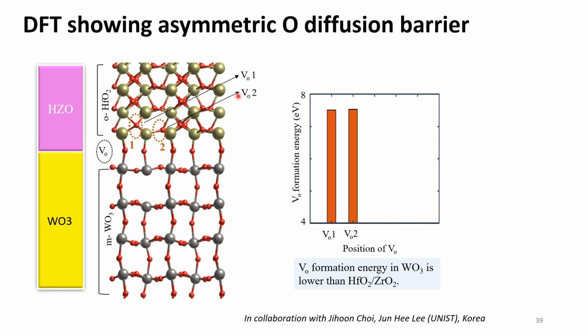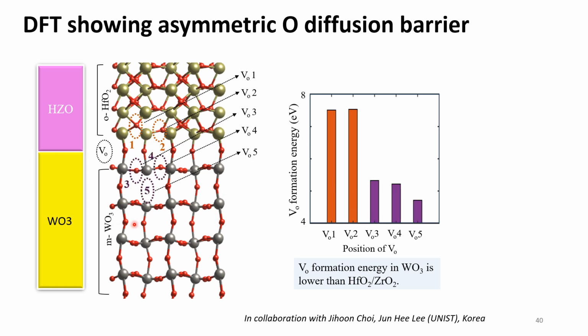So here you can see that on the top we have orthorhombic hafnia, and at the bottom we have monoclinic tungsten oxide layer. Next, we have deliberately created some vacancies at the hafnium oxide layer, which is vacancy number 1 and 2, and we have calculated the vacancy formation energy for these positions. Next, we did the same. We created vacancies at tungsten oxide layer and calculated the formation energy for those vacancies. So here you can see that the vacancy formation energy for tungsten oxide is smaller compared to that of hafnium oxide, meaning it's easier to form vacancies in the tungsten oxide layer compared to hafnia layer.